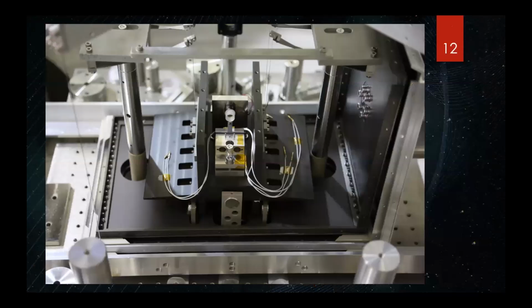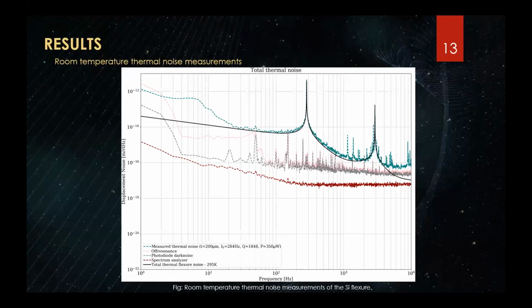And this is how the cavity looks when it's opened. It's a 20-liter box that you're radiatively cooling, and all of this is radiatively cooled. So, first results: we did room temperature thermal noise measurements, and you can see that the measurement is almost in line with the predicted model, which is the black trace. This was done on a 200 micron flexure with a resonant frequency of 284 Hertz.